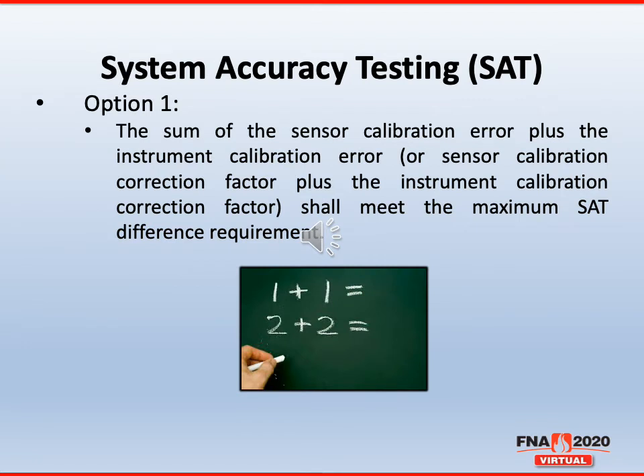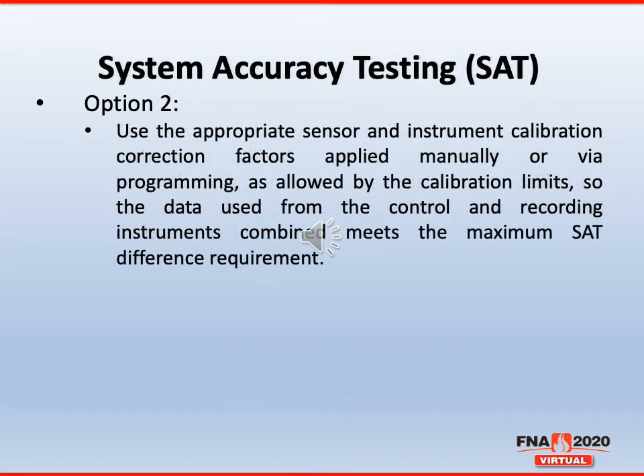Option 1, the sum of the sensor calibration error plus the instrument calibration error, or you can use the sensor calibration correction factor plus the instrument calibration correction, shall meet the maximum SAT difference. In other words, you're taking the calibration report from your process instrumentation and the calibration reports from the load thermocouples, combining them together, and as long as they're within the allowable SAT tolerance, that meets option 1 of the alternate SAT. Option 2, use the appropriate sensor and instrument calibration correction factors when applied manually or via programming as allowed by the calibration limits of AMS 2750. So when the data used from the control and recording instruments combined meet the maximum SAT difference.